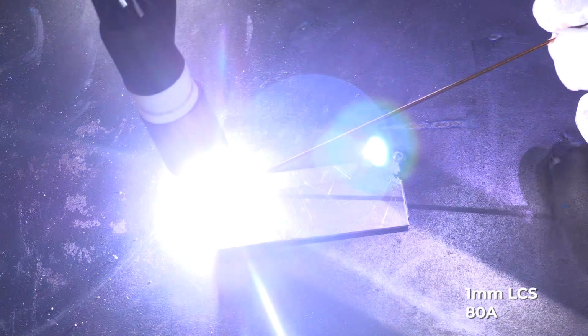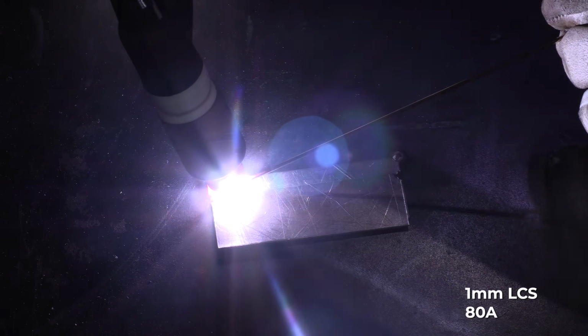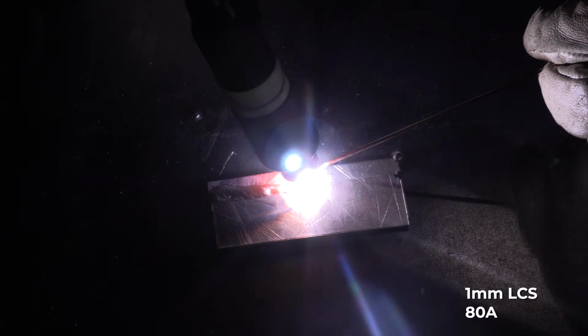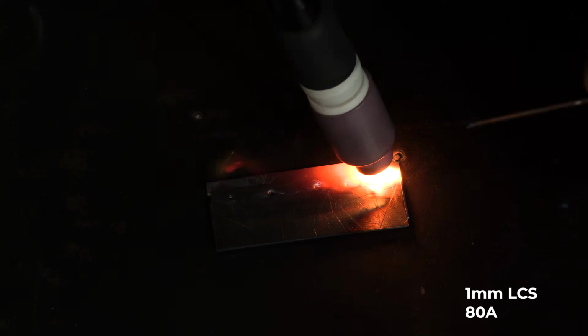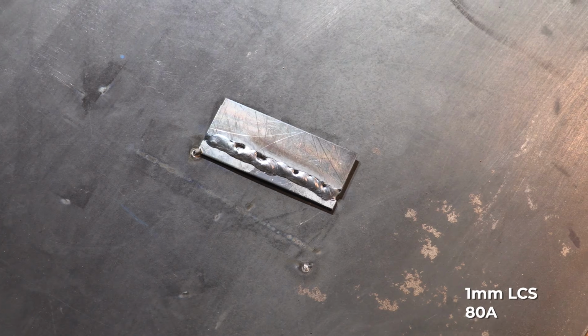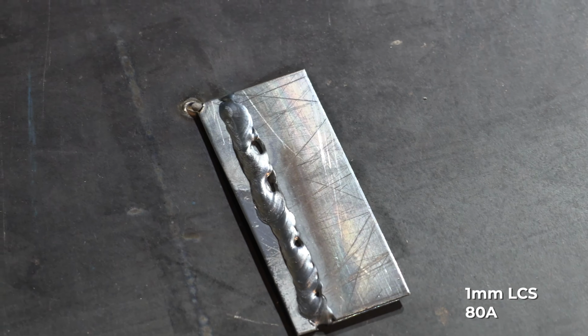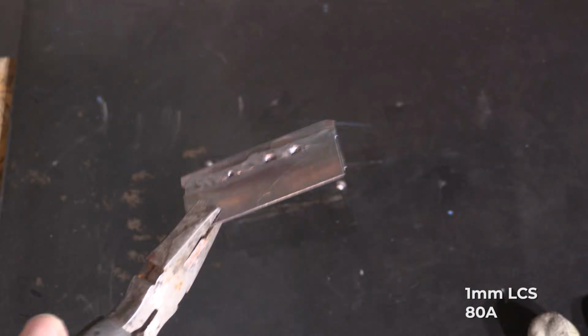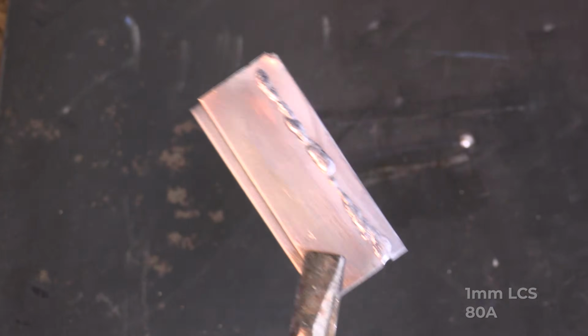Here I have 1mm low carbon steel. I'm going to weld a lap joint with no copper backing or chill at 80 amps. As you can see, it's far too hot. It's burning through the material, blowing holes, and it's just too high an amperage, even if I move quickly.